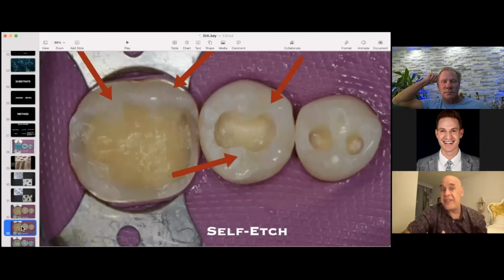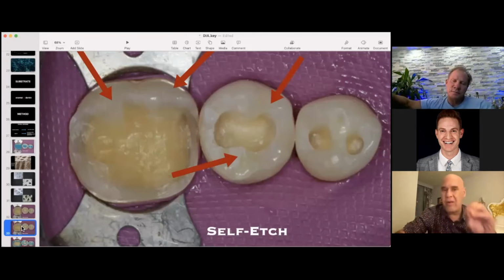And the reason for that is because your self-etch adhesive is not capable of properly generating a good mechanical retention and a good bonding to enamel on its own. I don't care what product you use. You need to etch enamel with phosphoric acid. Dentin, not necessarily, but enamel 100% of the time.